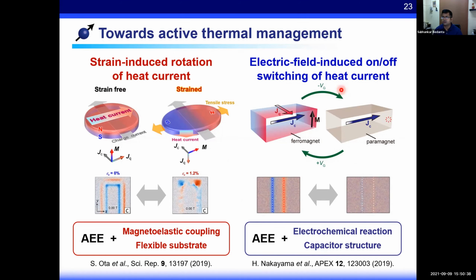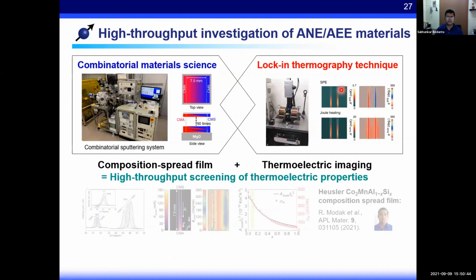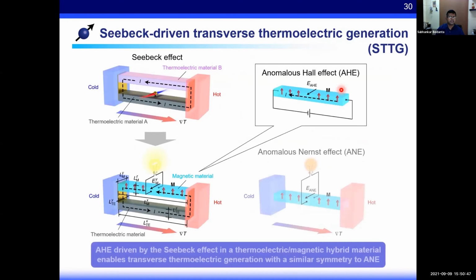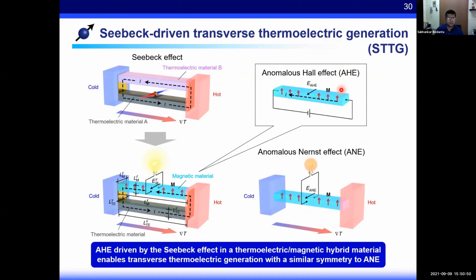So maybe I will ask one question. So in slide 30, yeah, you mentioned this device geometry. In reality, when you make such a device, is it really on top of each other with a gap, or is there an insulator in between? Actually, regarding the device dimension, meaning the size of the magnetic and thermoelectric materials, the gap should be as small as possible. If these materials are directly attached to each other, the shunting effect reduces the transverse thermopower. So we inserted the MgO substrate between them.